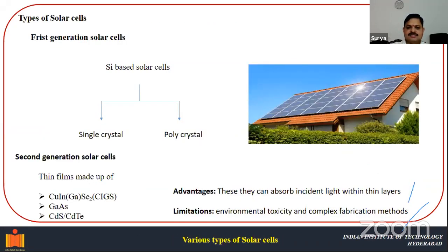So now the question is, what kind of solar cells do we have? We have the first generation solar cells. These solar cells are silicon based solar cells, either single crystal based or polycrystal materials. For the people who do not know, a single crystal is one in which all the grains are oriented in one direction, whereas in polycrystal many grains have different orientations. Like in a single crystal, if I say silicon 111, that means all the grains are oriented in the 111 direction. Whereas in a polycrystalline material, you can find different grains like 111 grain, 100 grain, 110 grain, and so on. So the solar cells that we are seeing in today's market are based upon silicon single crystal solar cells, and sometimes people also use polycrystalline silicon solar cells.